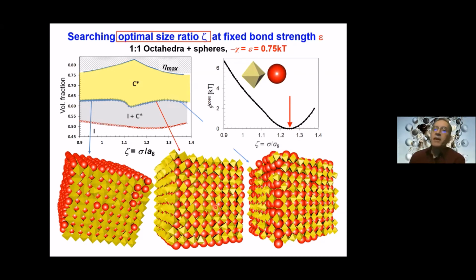It looks like this. Now, visually, there is an observation I make. If you look at this case, when the spheres are small, the large octahedra are touching their neighbors, creating small gaps where the smallest spheres nestle. While in this other case, for larger spheres, it's the other way around. Now the largest spheres are contacting their neighbors and creating small gaps where the small octahedra nestle. Now in this phase, it's different. For the optimal case, neither one is dominating; both are contributing equally in contacting neighbors and creating this geometry in this structure. Of course, that's just a human interpretation.